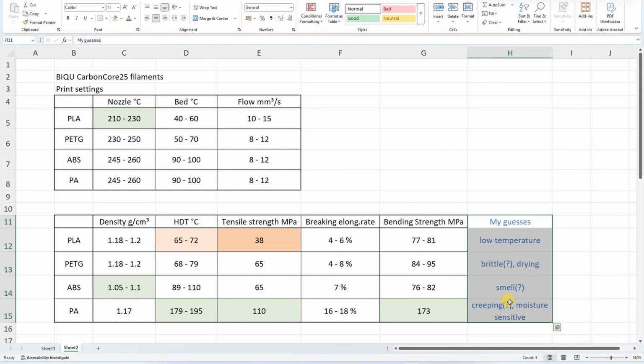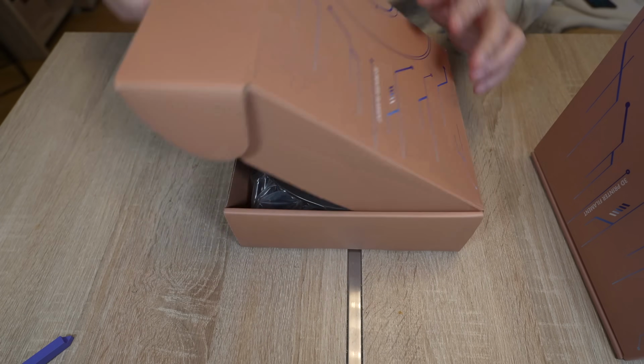And these properties are just my comments. I know that PLA has the lowest temperature resistance among these four base materials. PETG is more brittle and probably requires drying. About the ABS, quite a good material, but we have to see how much smell we have during the printing, and of course it is recommended to print it inside an enclosure and ventilate the room after the printing. And about the nylon, usually I experience more creeping with the nylon, and it is very moisture sensitive, especially in the carbon fiber version. Let's start with unboxing PLA.